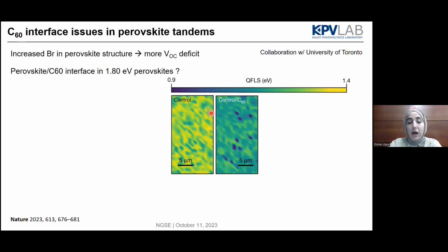Maybe I need to first show here how on the surface of the perovskite you might have really low quasi-Fermi level splitting areas, up to 0.9 electron volt areas, that are really affecting the perovskite silicon, perovskite C60 interface. This is basically because of band misalignment, it might be energy level pinning, or halide migration that's causing this effect.